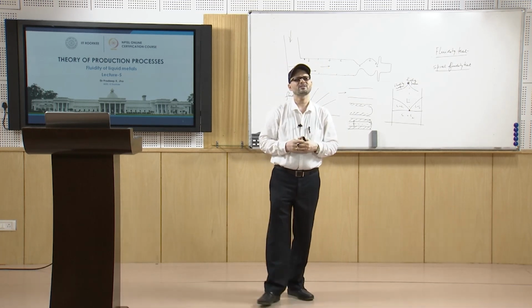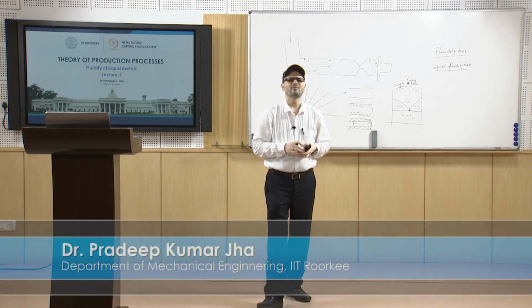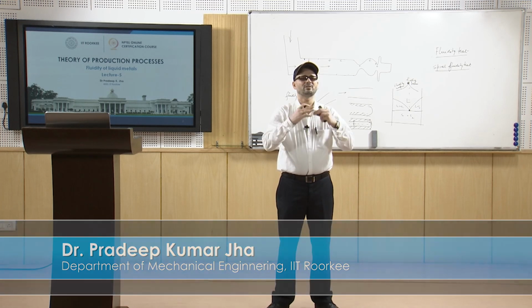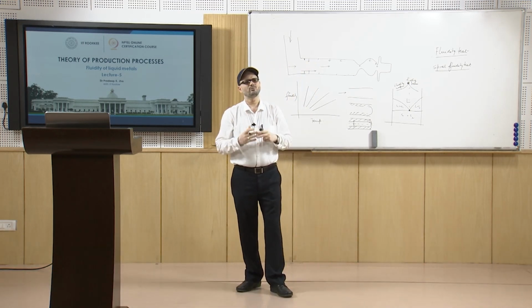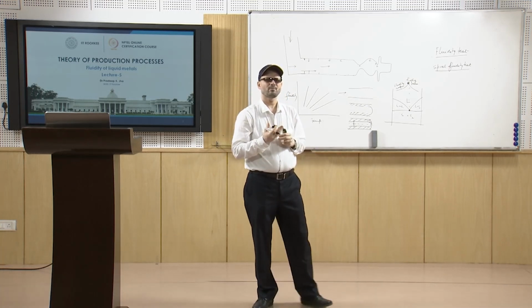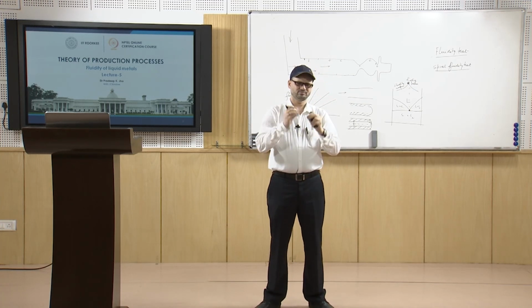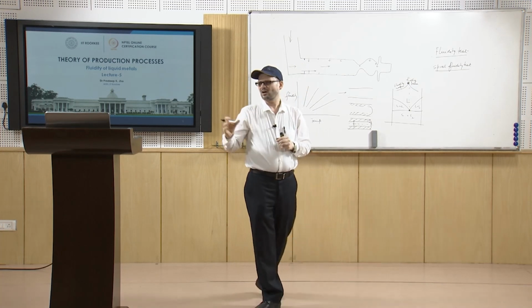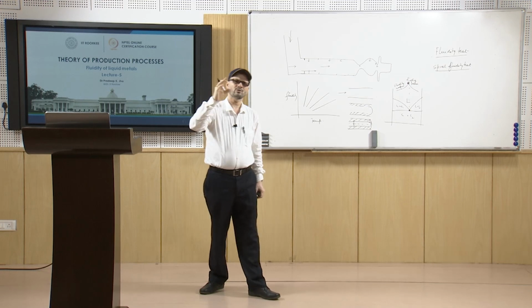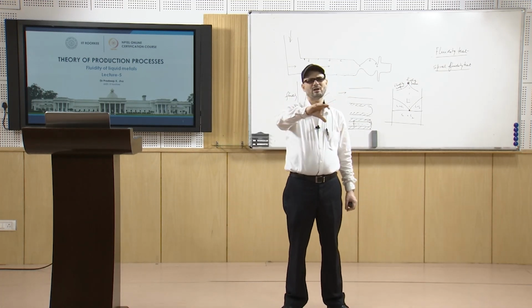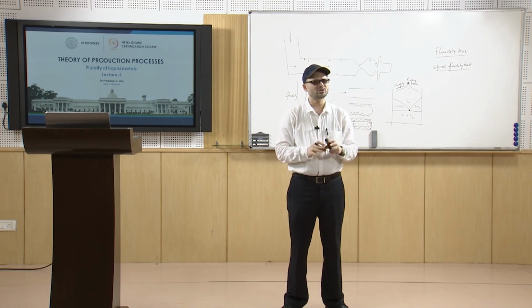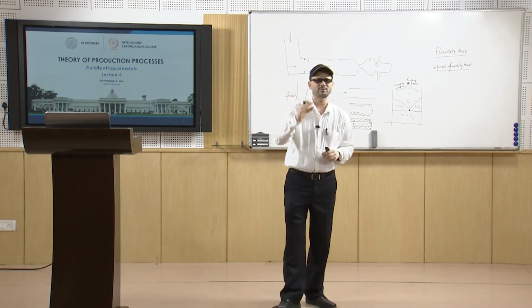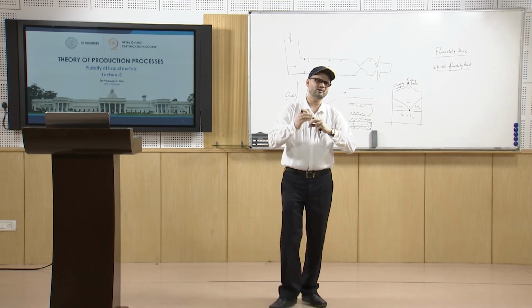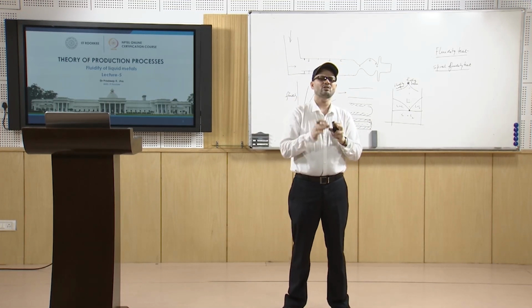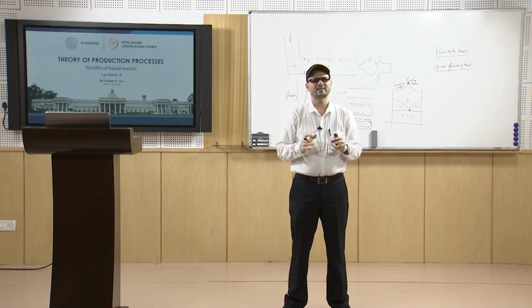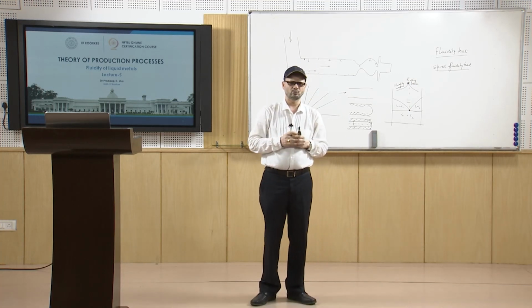Again, the fluidity depends upon many factors, as we discussed, like the compositional factors, the surface tension properties, and whether a surface oxide film is formed. There are different kinds of properties which drive this property. Based on that, you can ascertain the fluidity by the fluidity test. When you cast any material, you can run the fluidity test and see whether you have adequate fluidity. Once you have adequate fluidity at a particular pouring temperature, you can ensure that the liquid metal poured into the cavity will go into all the corners and fill all the details of the cavity. So, this is how the fluidity test is carried out. Thank you very much.